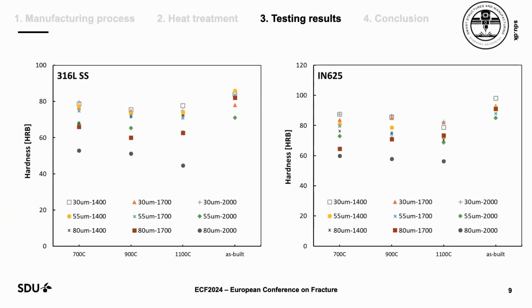We also did hardness testing, and in hardness testing we also saw the same behavior. So in the case of 700, we had better hardness, so we applied Rockwell hardness testing here, and we saw that the 700 had a better hardness when compared to the others, but lower than the as-built. And this is also in accordance with what we see from the literature. So mainly when it comes to hardness, again, grain sizes and this recrystallization are the main factors affecting the hardness of the material. And that's the reason why we see smaller hardness when we compare to the as-built samples.